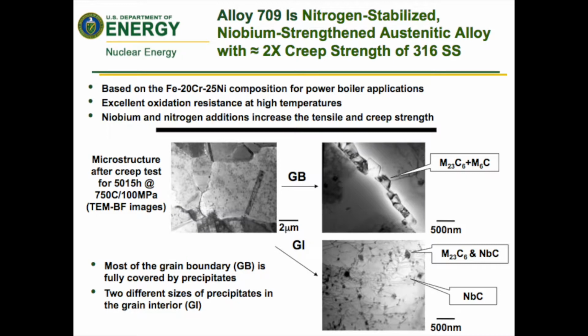Now, alloy 709, a nitrogen stabilized, niobium strengthened austenitic alloy, has about twice the creep strength of 316 stainless. So if and when we're able to get this in the code, it will provide designers a dramatically enhanced material that they can use, again increasing their design envelope and their safety margins for the reactors that they can build with this stuff.